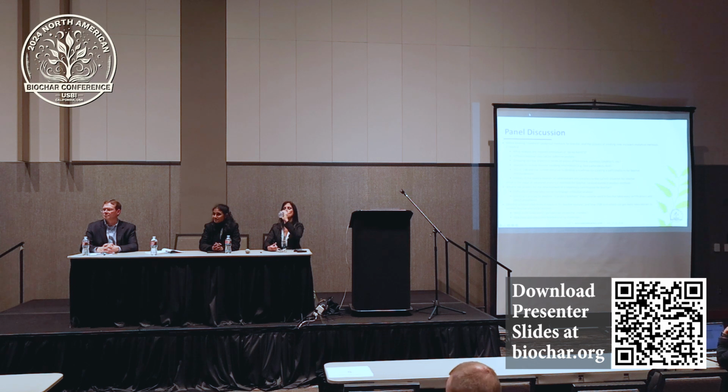Does that answer your question? Is the application going to be soil amendment, or what was the application? When I answered that question, there was one more point. I asked them, what did you make it out of? If you're making it out of the treated wood from your kids' playground leftovers, okay, as long as it was clean biomass feedstock going in, I'm not worried. The application is going to depend a lot, but what I'm looking for as a chemical engineer is: is it undercooked, overcooked? And was there the right escaping of volatiles? That's the question I'm trying to answer: did I make char? Did I do pyrolysis?